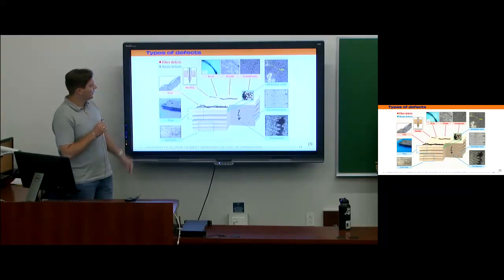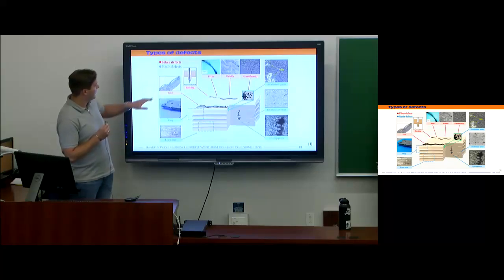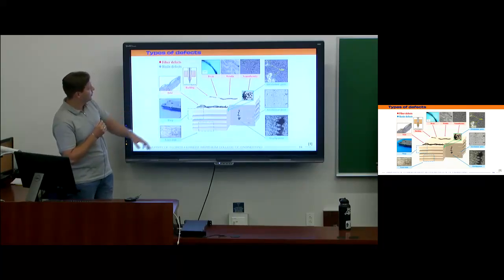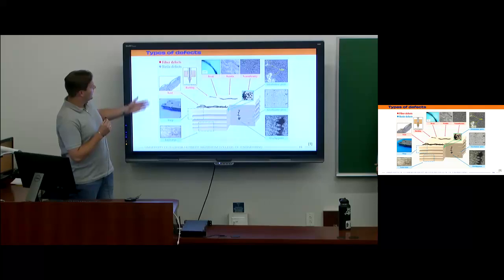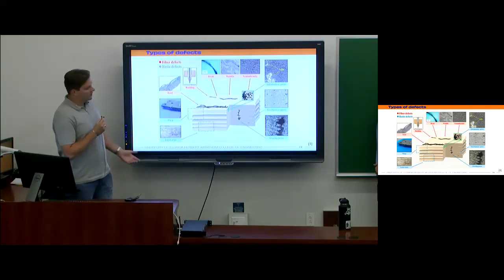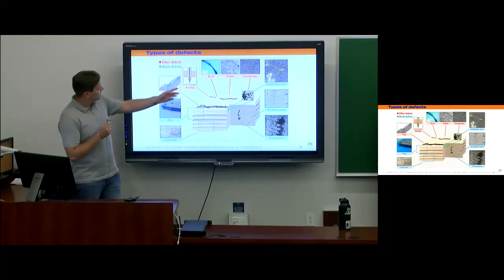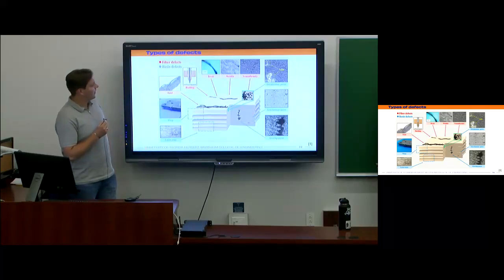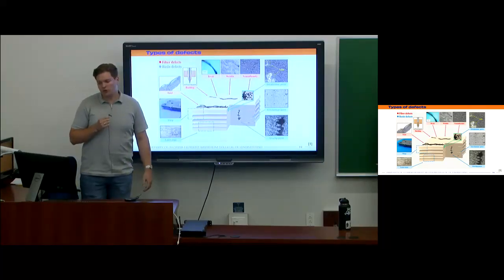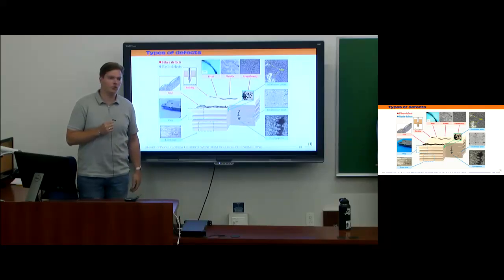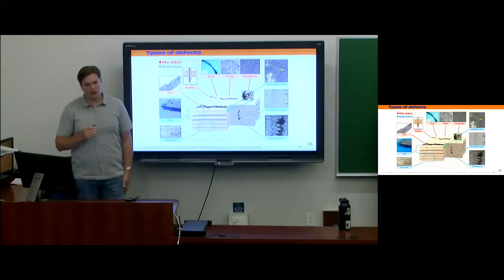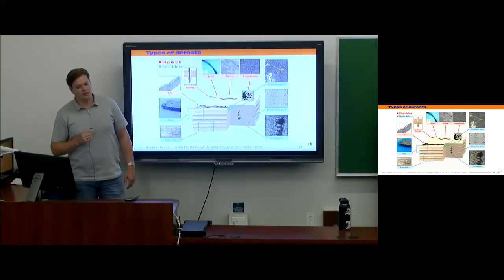They're shown in this figure and categorized into fiber defects in red and resin defects in blue. So for the fiber defects, things can be found like twisted fibers or fibers that buckle within the nozzle, broken fibers shown up there, wrinkled fibers or non-uniform distribution of fibers, and all of these lead to fibers not reaching their full reinforcement potential. So whenever they're misaligned or broken, it leads to a significant reduction in mechanical properties.